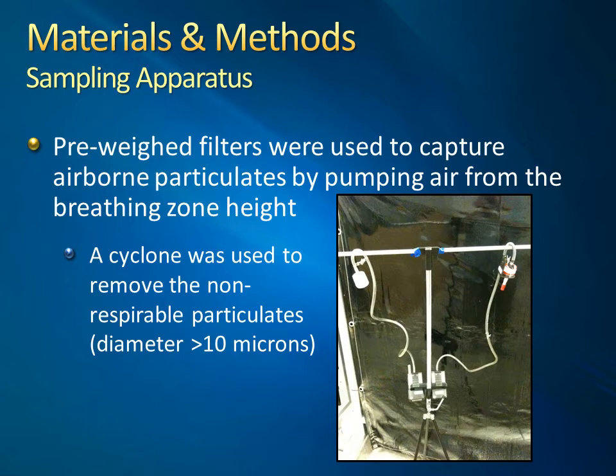The filter assembly was attached to a pre-calibrated air pump to sample the air at the recommended rates of 2.0 and 2.5 liters per minute for the aluminum and silica respectively. This method required a sampling volume of around 1,000 liters of air.